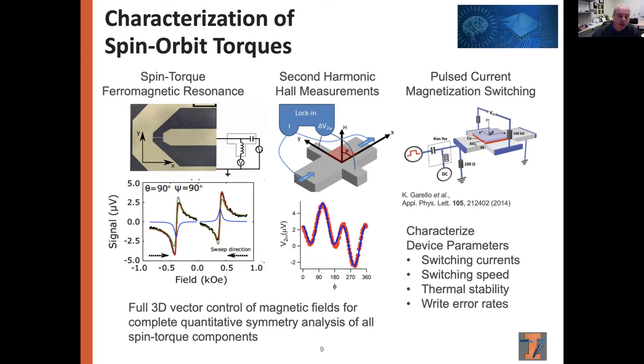We have developed new metrology tools for these spin orbit torques early on. And so we have two that are really the workhorse for characterizing the efficiency of these electric spin torques. One is called spin torque ferromagnetic resonance, where we excite magnetization dynamics using gigahertz microwave excitations. And the other one is called second harmonic Hall measurements, which is a much lower frequency type of technique, but using essentially similar ideas.